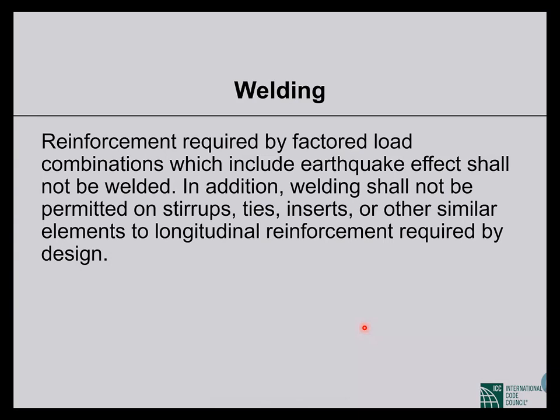that are needed for sustaining earthquake load. In addition, welding shall not be permitted on stirrups, ties, inserts, or other similar elements to longitudinal reinforcement required by design. So you cannot weld your tie with the longitudinal rebar, or weld the stirrups with the longitudinal rebar of your beams. So this is important from the seismic design point of view. I think that's all I have.